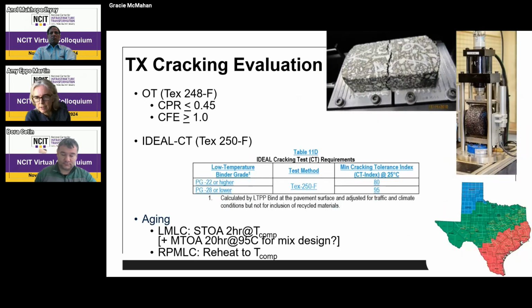Next slide, please. For the cracking, we're also doing the repeated load test, the overlay tester, which is the same test as being done in New Jersey, and then the IDEAL-CT, which New Jersey is also doing on the right-hand side there. We have proposed that the threshold should be tied, in this case, to the PG low temperature grade of the binder. Next slide, please.